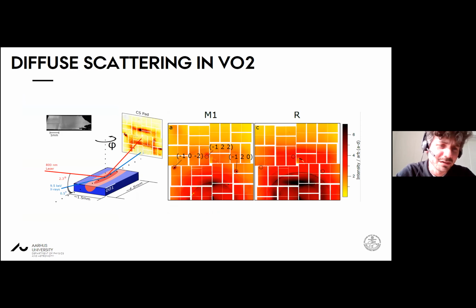Okay, the experiment is actually very simple. We just put the sample in a grazing geometry. We come in with the laser and X-rays, and this is how it looks on the detector. This is in LCLS now. We have the CSPAD, which gives this unique pattern to the image. I've highlighted here three monoclinic peaks which disappear in the high temperature phase. I've also highlighted the diffuse regions of the system, which we're going to look at here. So we expect these to disappear, and we expect this intensity to appear. And the question is, how and when does this occur?